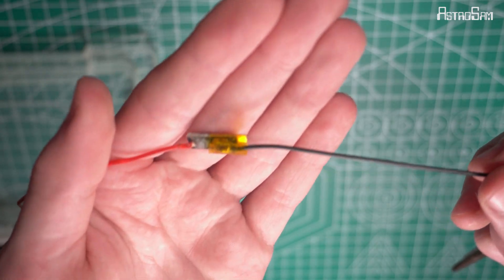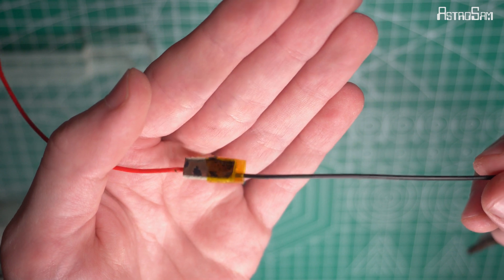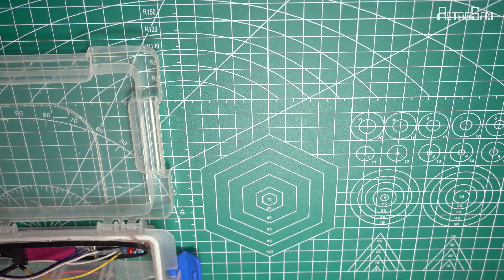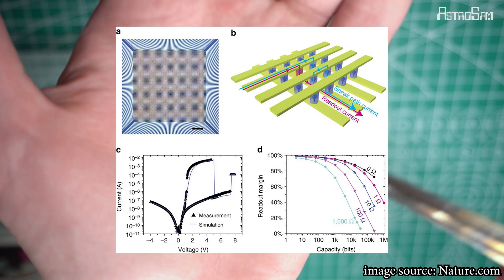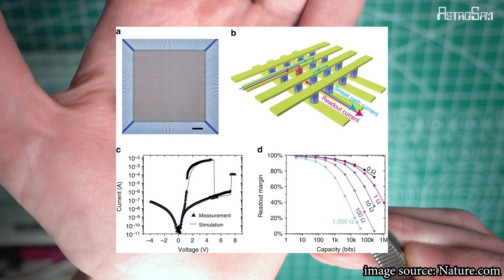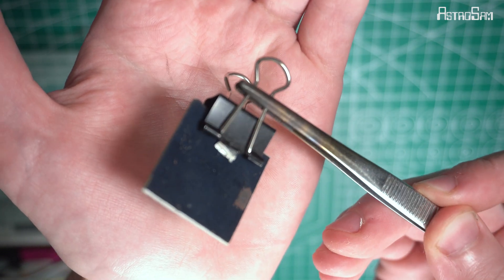So I had to try a different method. This next one used a PCB layer — I created the copper sulfide layer and used a piece of aluminum pressed against it with a piece of Kapton tape as a connected electrode. Unfortunately, this one also did not work very well and was sensitive to even a small bump. I also wanted to make it as expandable as possible because usually these are used in arrays, so you want it to be easy to make a whole lot of them and connect them together. Another test used a copper sheet and a piece of aluminum held on with a binder clip. Just rubbing the surface with my thumb, a lot of it comes straight off, so I needed to think of a better way.